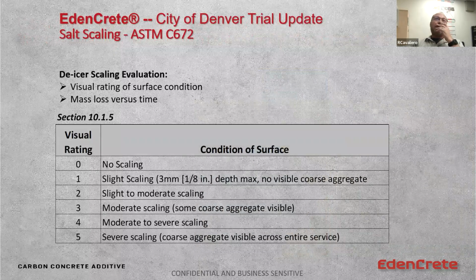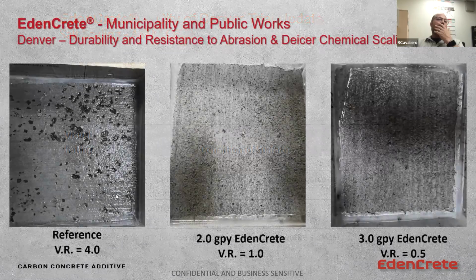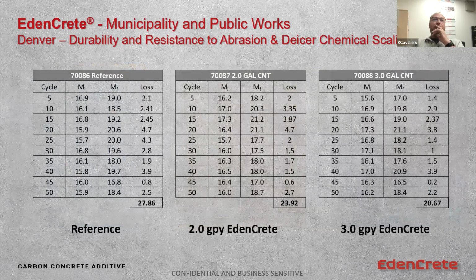We ran de-icer chemical scaling, which is a combination of ASTM C672 with another Canadian standard. First you do a visual rating of the surface and how far scaled it is, 0 being no scaling and 5 being severe with coarse aggregate visible. These samples were done by Martin Marietta, who have a concrete plant down on Quivas. You can see the reference has a lot of dark sections, where the concrete is actually delaminated and scaled. The EdenCrete section maintained and has a better visual rating. When we combine what was lost, the mass loss goes from 27.86 for the reference to a drop of like 14% and almost 26% for the EdenCrete.